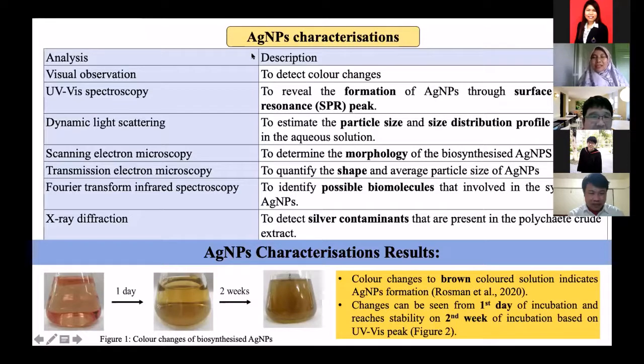So actually, yes, we synthesize within one day, but we also measure the formation every single hour to see the silver nanoparticle formation, and we can detect the formation started after 4-hour incubation. But the most significant one is after 1 day. That's the most stable one. And for the sample that you apply, just for how long? We did the synthesis up to 2 weeks to see. 2 weeks. Yes. How about your opinion? I think it's too long time, right? Yeah, because we want to see any effects during the time.